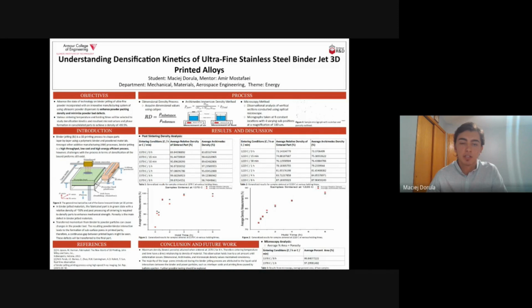Powder-binder interaction leads to the formation of subsurface pores in printing parts. Therefore, a continuous gap between printed layers may be seen. If the powder dispensing system cannot eliminate the subsurface pores by adding newly deposited powder, defects will be transferred to the final part. By gaining designing experience, 3D printing, and characterization aspects of the additively manufactured parts, it was possible